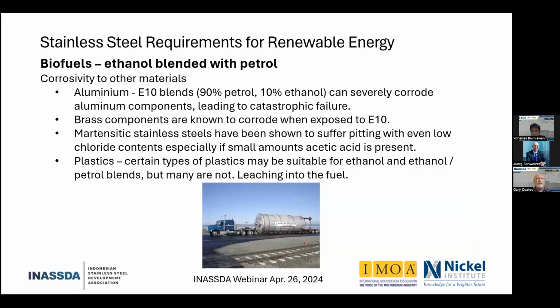Just as a comparison, other materials: aluminum, with the E10 blend, which is only 10% ethanol, which has really been the common amount in North America anyhow, severely corrodes. Brass components will corrode. The martensitic stainless steels, which have that minimum level of corrosion resistance, have suffered pitting in some environments because of the chloride content and small amounts of organic acid, acetic acid, that is present. Certain plastics are suitable, but we have a real problem when plastics that aren't suitable but are suitable for the petrol product are used, and then you put in the blended material, and the plastic material leaches into the fuel and then gums up the engine. So you have to be very careful with using plastics.